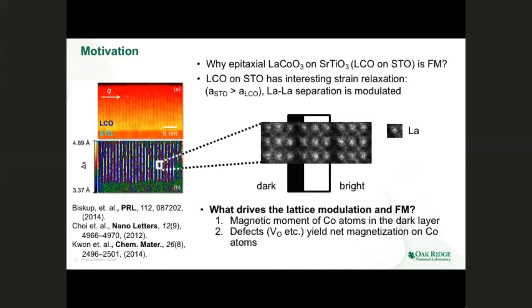The second effect would be that maybe there are oxygen vacancy defects, again within the dark layers, and the oxygen vacancies would be able to drive the magnetization on the cobalt atoms so that the material would be ferromagnetic. So there are two different mechanisms by which the ferromagnetism could be possible. Basically, in the first mechanism, it is the rotation of the cobalt octahedra that drives the ferromagnetism, and the samples will still be stoichiometric. The second mechanism suggests that the samples should be non-stoichiometric and there should be oxygen vacancies.